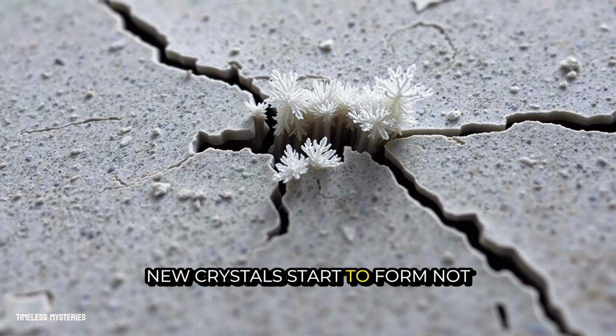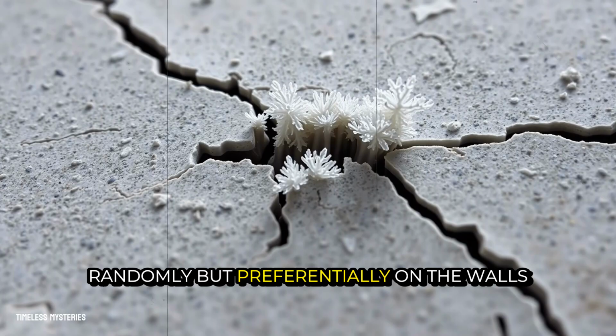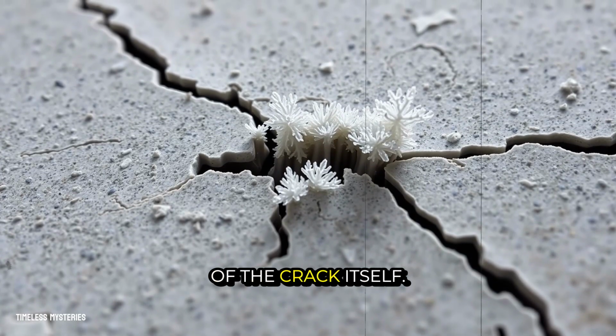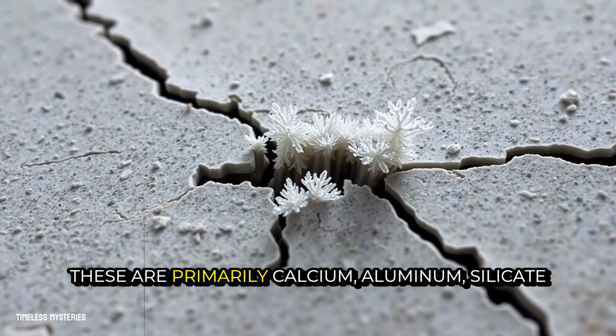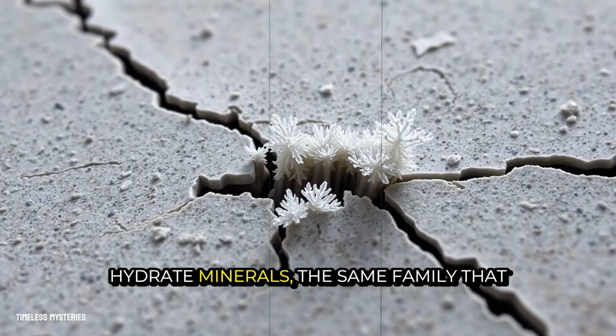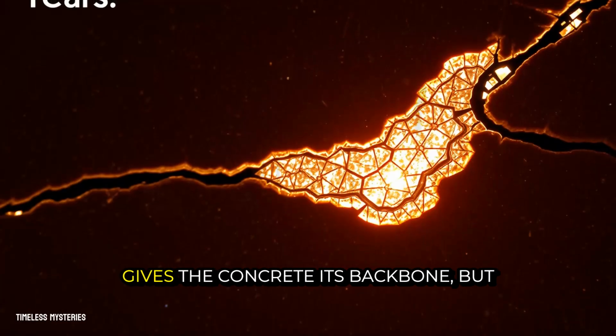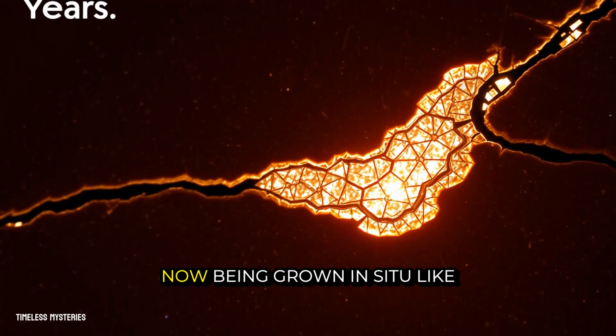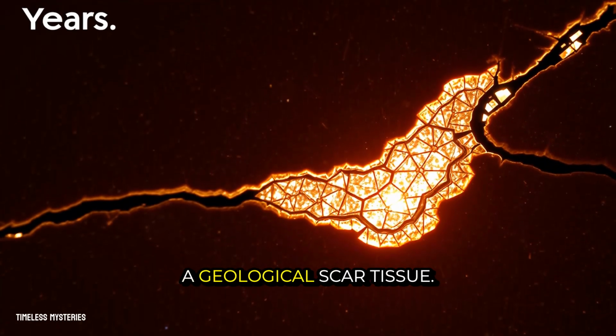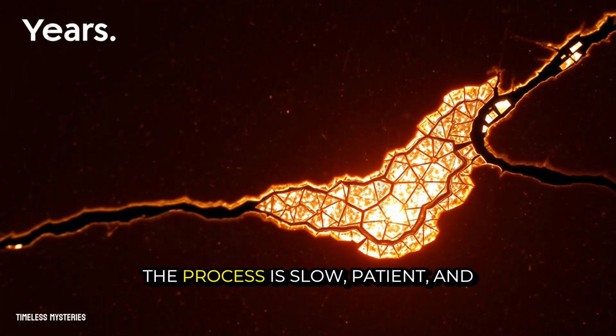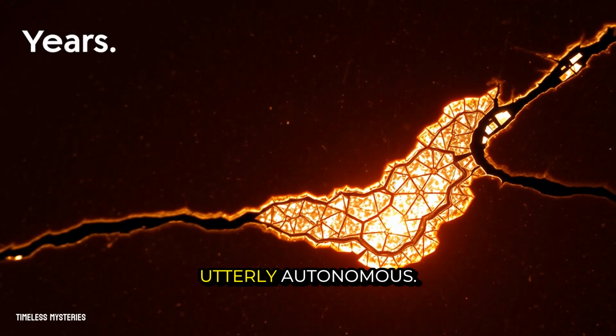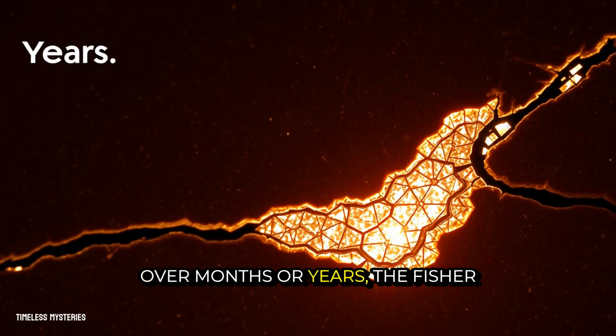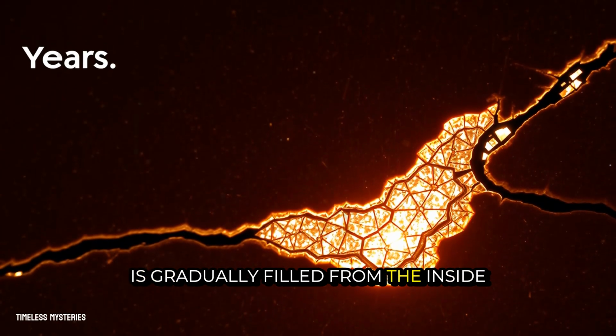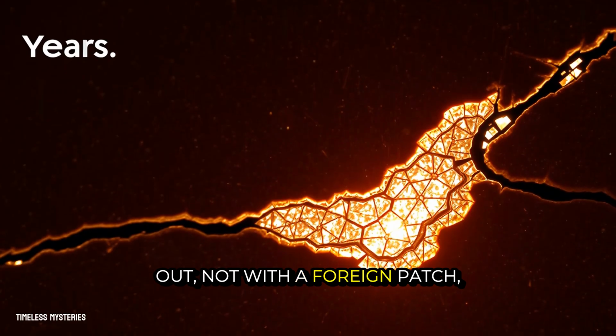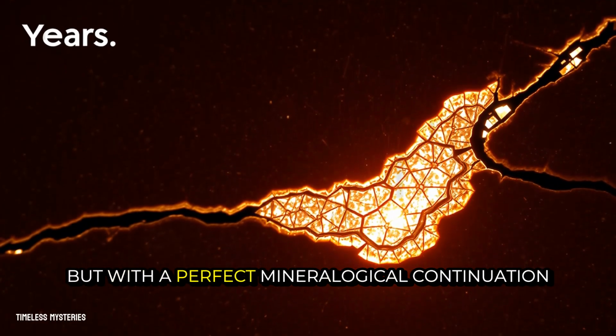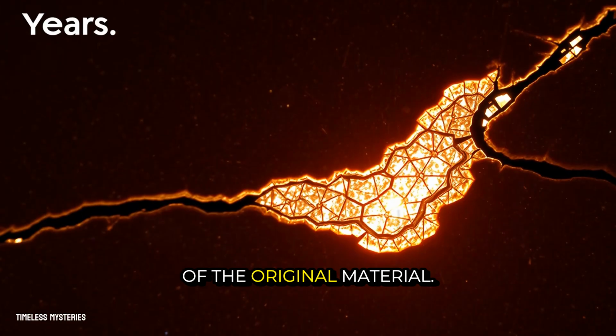New crystals start to form, not randomly, but preferentially on the walls of the crack itself. These are primarily calcium-aluminum silicate hydrate minerals, the same family that gives the concrete its backbone, but now being grown in situ, like a geological scar tissue. The process is slow, patient, and utterly autonomous. Over months or years, the fissure is gradually filled from the inside out, not with a foreign patch, but with a perfect mineralogical continuation of the original material.